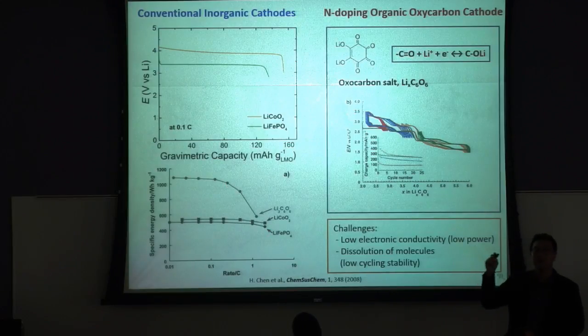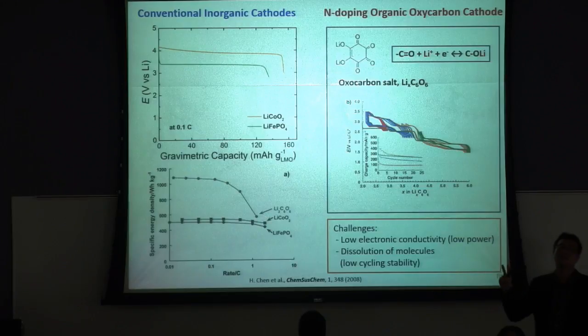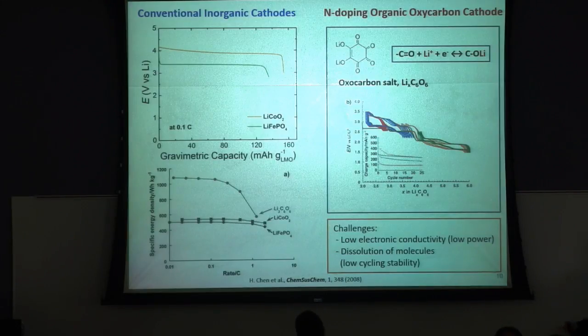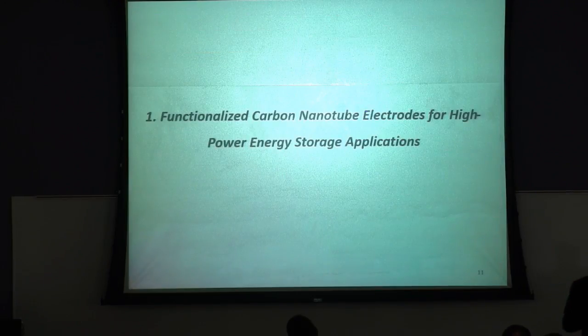That's the first issue. The second issue is the low cycling stability because of the dissolution of this molecule during the cycling process. In the initial cycle, the capacity is pretty high, 400 milliampere hours per gram. But within 10 cycles, these molecules dissolve in the organic solvents, so we gradually lose this capacity. So this low rate performance and poor cycling stability are critical issues of this type of organic battery material. Okay, so from now, let me introduce how we can solve these issues of organic materials.